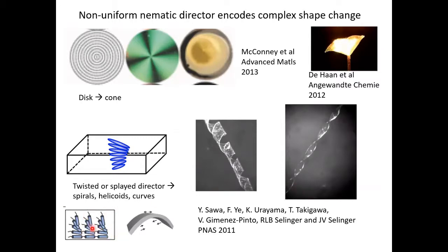And we can have a material where the nematic director is pointed, say, north-south on the top and east-west on the bottom. When you heat this material, it will shrink more on the bottom and shrink less on the top, and it makes the whole thing curve. So you would think if you design just the right director field, that is to say the orientation of the nematic order as a function of position on your sample, you could go from any shape to any shape. You would think you could make a little flat piece of plastic, the shape of a postage stamp, pop up into a bust of Einstein. You could make anything if you knew where to put the nematic director field and if you had a way to fabricate the sample that way.